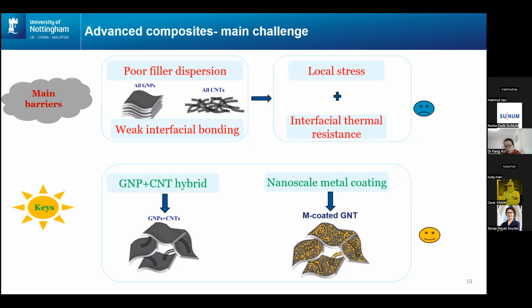Here we propose to use molecular level mixing to introduce nanoscale metal coating onto the graphene and carbon nanotube structure. So to achieve the metal coated graphene nanotube, we will see how we are doing with this. Hopefully, if we could get satisfied dispersion and achieve atomic level coating, we will see something promising.